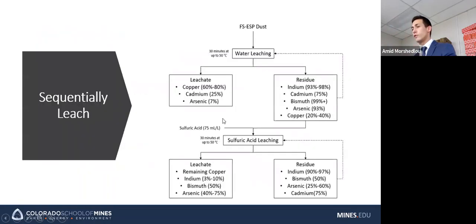Another thing we looked at was doing water leaching first. From here up, it's the exact same as the last slide I showed you. But what we'll do is take this residue and leach it with sulfuric acid. The remaining copper goes into solution, along with some of the indium, half of the bismuth, and a good chunk of the arsenic. The residue gets upgraded in indium, some of the impurities are reduced, and cadmium pretty much stays there.